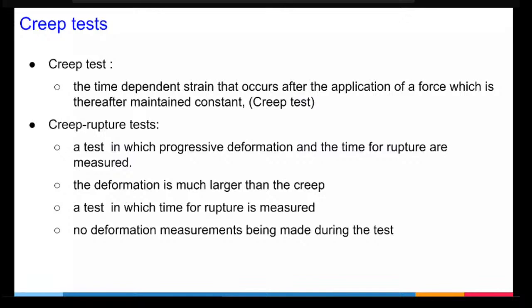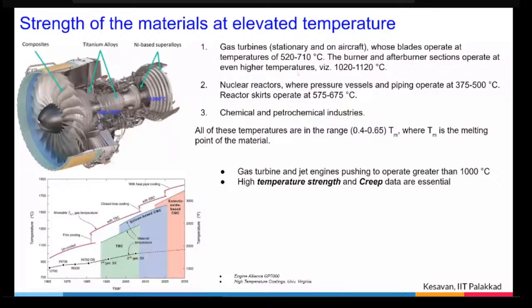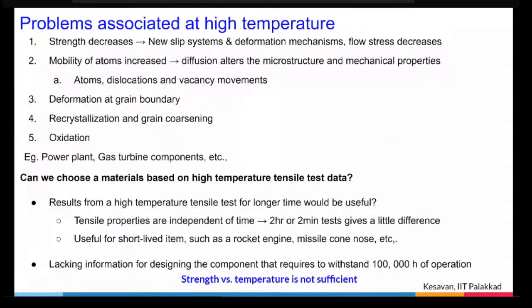Why are we doing this? Because these materials will experience difficulties at higher temperature. The moment you increase the temperature, there are several problems: strength decreases, mobility of atoms increases, deformation takes place at the grain boundary, recrystallization takes place, and oxidation. These are all problems, and all of these can be captured in creep data. Creep data will look like this: basically strain versus time. You can also plot strain rate versus time. At a constant load, you have a sample like a dog bone sample. You apply constant stress and heat the sample, or keep the environment at higher temperature, and measure the strain with respect to time. It looks curved like this.